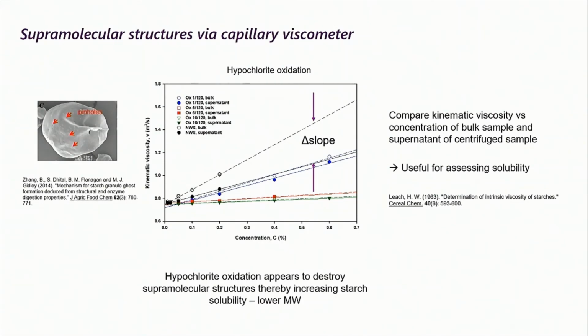So what I've done is I've had a bulk sample, I've measured the kinematic viscosities of that, and then I centrifuge that sample and take out the top 2/3 of the centrifuge sample as the supernatant, and I repeat that process. When there's that slope difference, that indicates that there's larger structures. It's not a completely homogeneous solution, and so that indicates those supramolecular structures that exist.